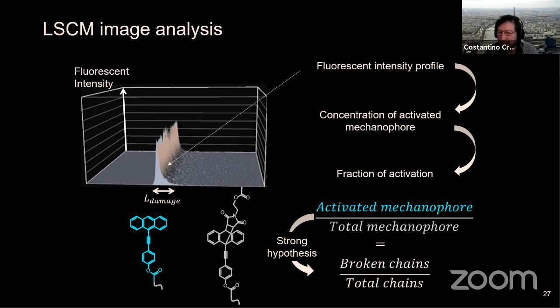Now, that hypothesis implies that the randomness of the chains is more important than the strength of the bond, and that what is important is that you break the strand when it gets to its maximum extension. Then if you have a weak bond in there, which is our mechanophore, this will break. So every chain that gets stretched to its maximum extension breaks this mechanophore if there is one. If that's true, then I think our measurement should be representative. And I'll show you some data that, in my opinion, shows that indeed we are.